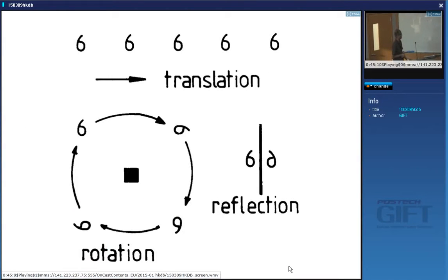We also need to think about symmetry. We've already talked about that by identifying crystallographically equivalent planes and crystallographic equivalent directions. So in the cubic system, you know, we had 6 cell edges, which all have exactly the same properties. If I change that to tetragonal, then the A axes are identical in the basal plane, but the C axis is different. So the symmetry changes, and now I have 4 equivalent 100 directions, not 6, okay? And so on.